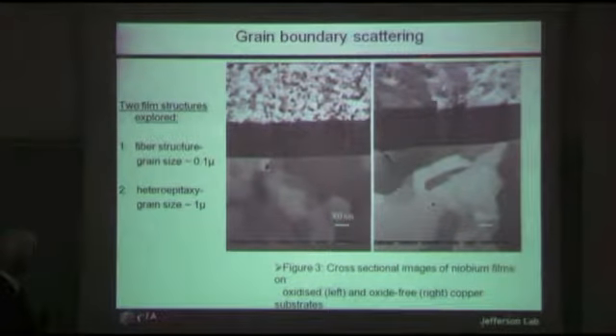Again, just to repeat, this is a little history. The two film structures that were explored by CERN were a fiber structure, which they created by oxidizing the copper surface to destroy epitaxy, and then they've also looked at large grain heteroepitaxial structures.